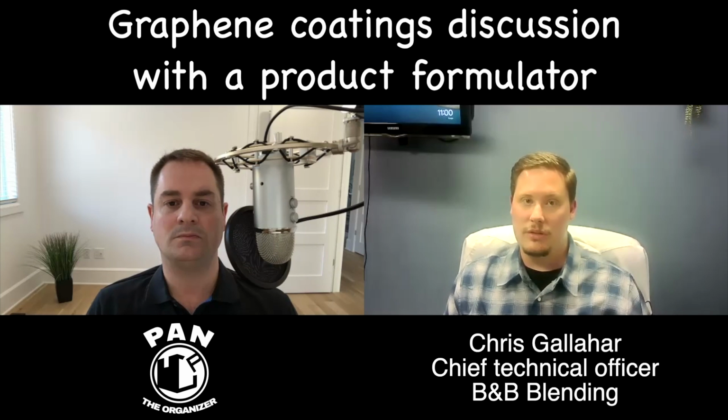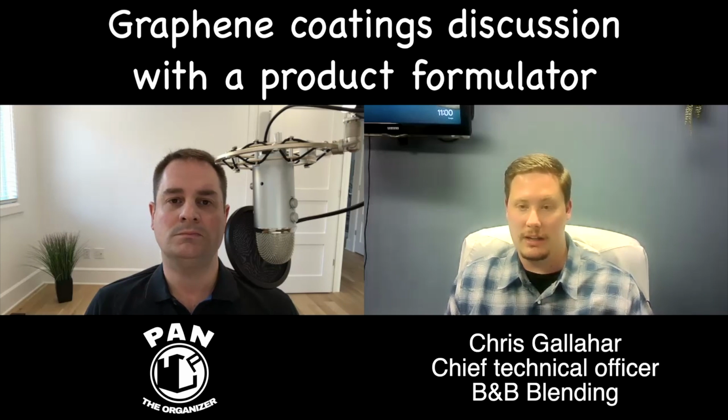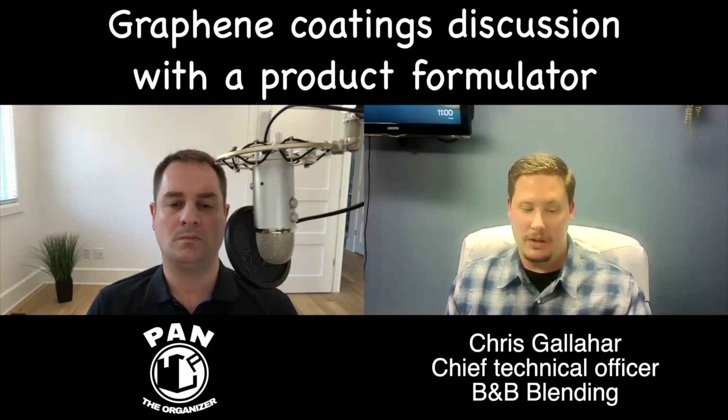What we're doing is we're using instruments in the lab that are capable of measuring coefficient of friction. We're using optical tensiometers to measure things like contact angle, QUV weathering apparatuses to accelerate wear on a UV basis. So basically a week in the instruments is like a month in real life, so we can accelerate it considerably. And using abrasion and washability testers that remove any sort of bias that we can have on it.